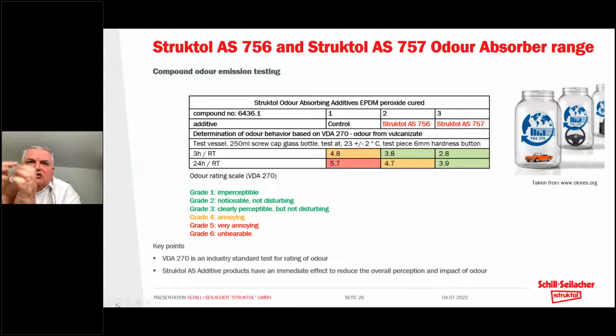So one of the test methods that we can use is a method called VDA 270. VDA 270 is an industry standard, if you like, that was adopted by the automotive industry and is used to assess all kinds of components and chemical combinations in terms of their odor generation. It is literally a nose assessment test. So you would have a glass bottle of defined dimensions, and you would place your sample in there and allow the odor to permeate into the atmosphere in the sealed glass bottle, and then have a number of people rate that by literally nosing and smelling that. And then we have a scale from grade 1 to 6, where we would say the first 3 grades are okay, starting to build a little, but okay. Grade 4 causes some concern, and grade 5 and grade 6 are really more or less unacceptable.